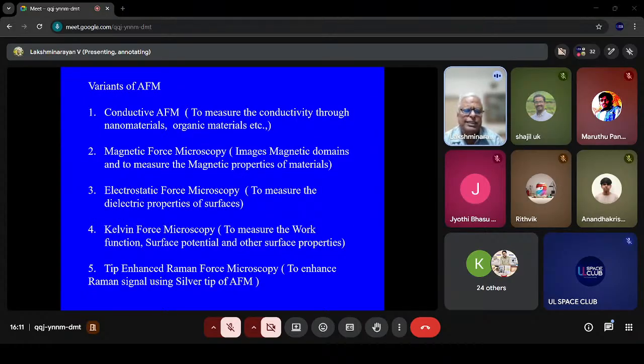So instead of silicon nitride, you use gold here for conducting AFM. Here you use nickel as a magnetic material tip. And when you scan the surface, you can see which regions have magnetic domains, and you can map the magnetic strength of the region. Similarly, you have electrostatic force, and you can measure the dielectric properties of surfaces, because you can have a particular charge on the surface by using some organic material. For example, a carboxyl group, when deprotonated, will have a negative charge, and an amino group a positive charge. So you can use those forces, those kinds of tips.